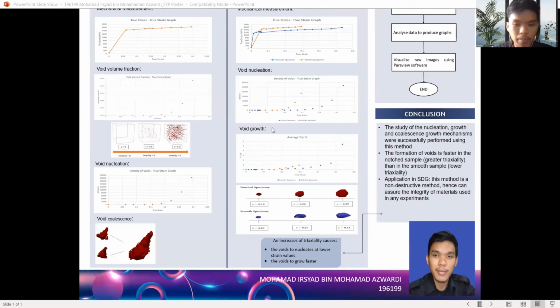Right, so the void growth shows the shape of the singular void. In the notch sample, the five largest voids grow faster compared to the smooth sample. It shows that higher triaxiality induces a higher void growth rate. The figure here also shows the evolution of the void shape across the deformation for the notch and smooth samples. And here we can see that the voids grow, and in terms of shape, they grow into a more spherical shape.